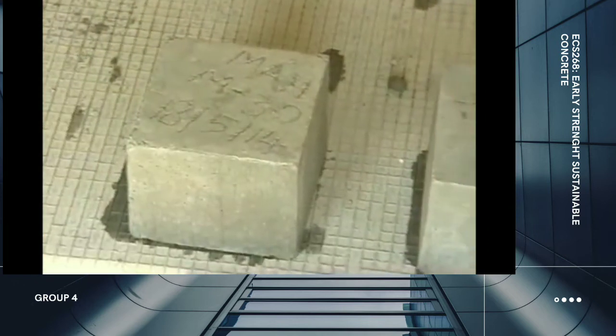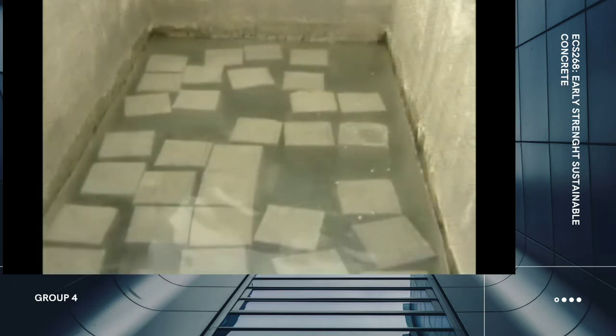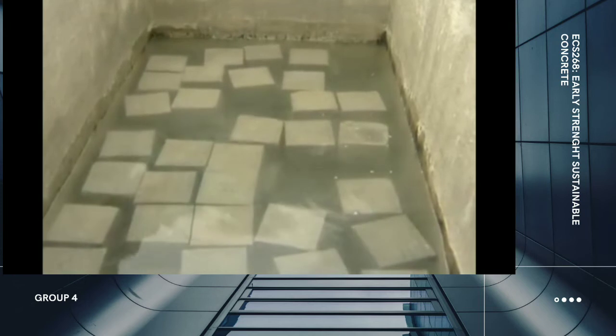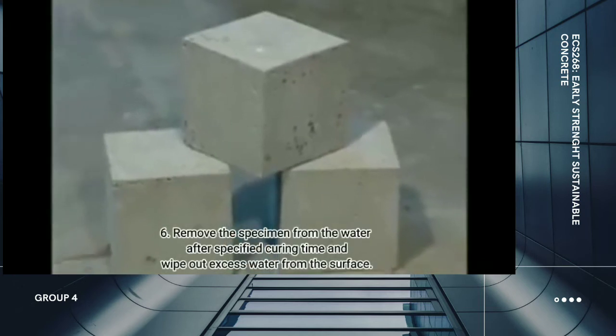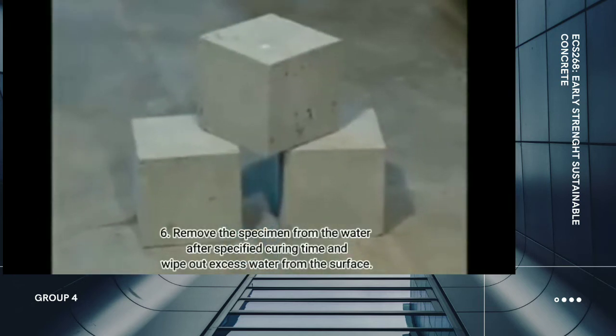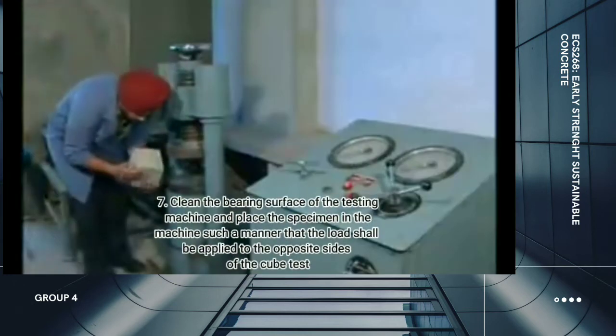The test specimens are stored in moist air for 24 hours, and after this period, the specimens are marked, removed from the mold, and kept submerged in clean fresh water until taken out prior to the test. Remove the specimen from the water after the specified curing time and wipe off excess water from the surface. Clean the bearing surface of the testing machine.